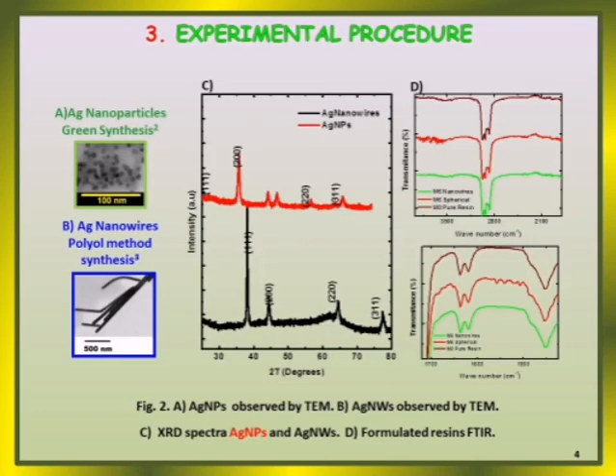The experimental work consisted of, first, round silver nanoparticles were synthesized by a green method, and silver nanowires were synthesized by the polyol method. We can see evidence of its formation in the left images, and in the central plot, X-ray spectra. The upper X-ray spectra corresponds to round silver nanoparticles, the red line, and the black X-ray spectra corresponds to silver nanowires. More details about the synthesis and characterization can be found in references 2 and 3.